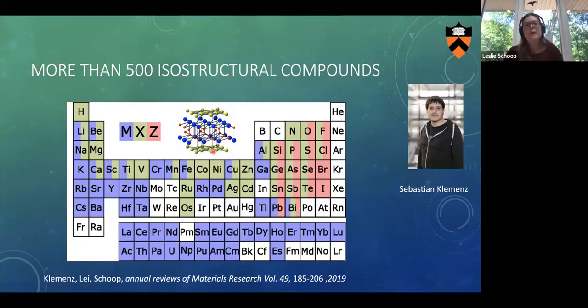But here I need to know if the square net has a certain electron count, like 6 per square net. And for that, I need to know the oxidation states of these atoms, because I need to know if the blue atom gives electrons to the square net, or takes electrons from the square net, or what the red atom does. And that is not always as straightforward as you would think, because often oxidation states are very hand wavy, and it's not an exact science. So we were thinking electron counting is probably not the best idea to fully understand it.